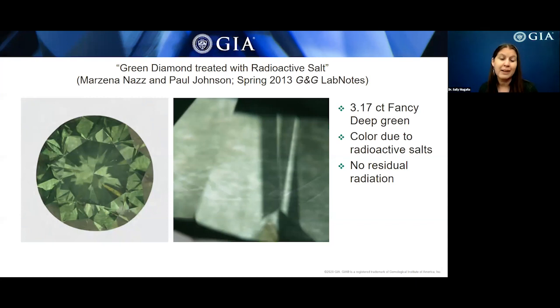Since diamonds irradiated in this way can have residual radiation, the authors tested the diamond using a Geiger counter. However, only background radiation was detected, indicating that the treatment likely had occurred decades earlier. Therefore, this diamond posed no radiation hazards at the time it had been submitted. And although rarely seen today, this sort of irradiated diamonds can still show up within the trade.